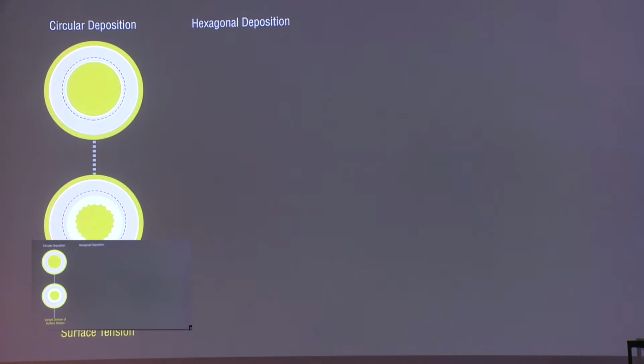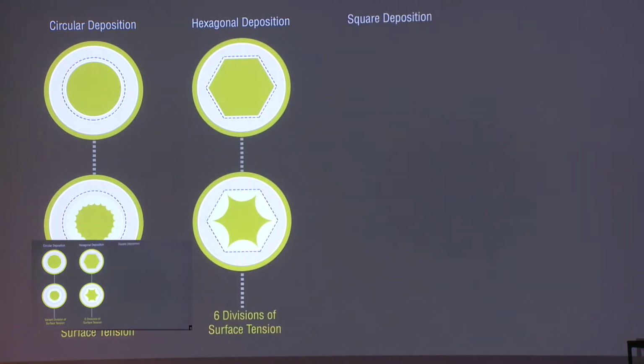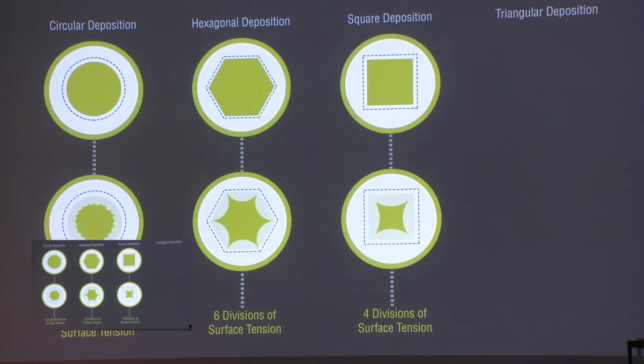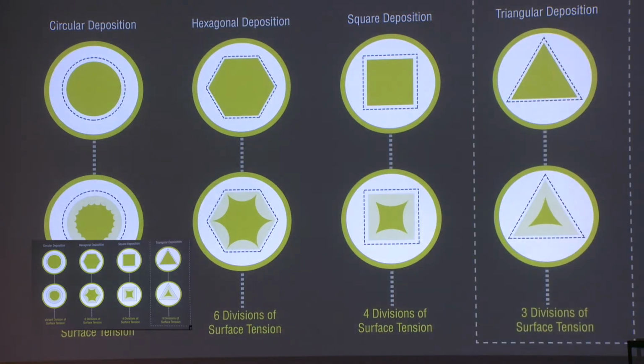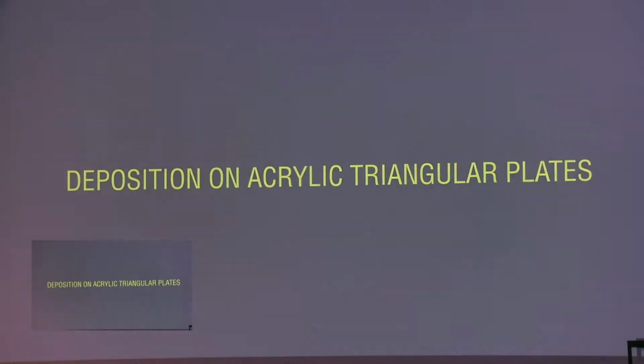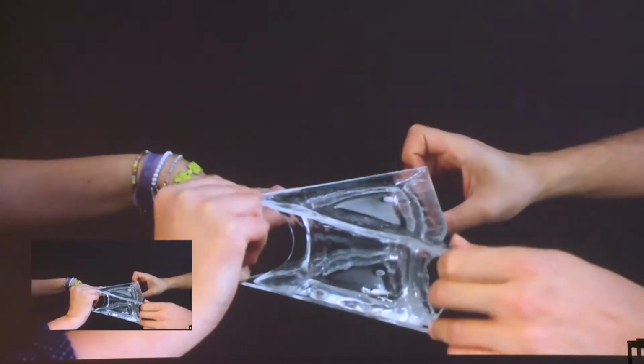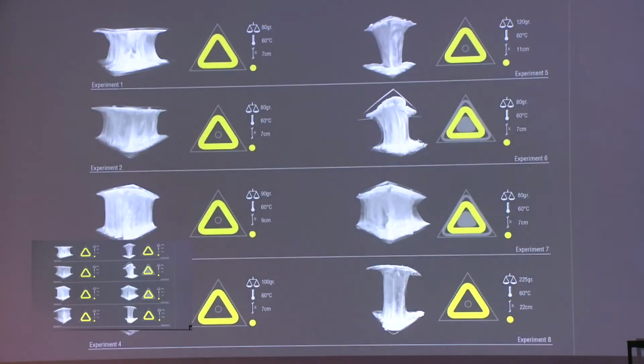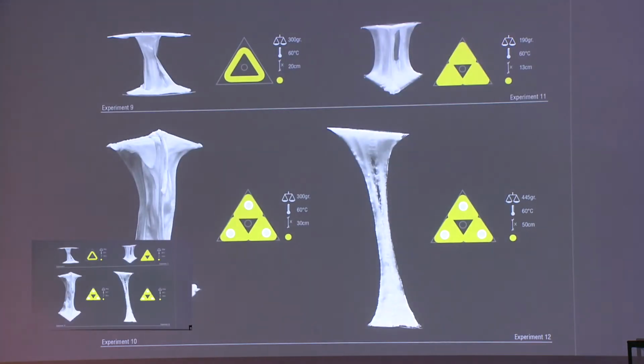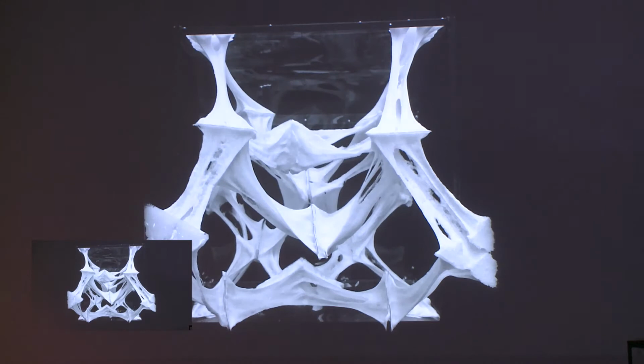After looking at all of those material simulation parameters, we evaluated which is the correct deposition and the correct shape of the plate that we need to use. So we came to the conclusion that the triangular deposition and triangular plate is optimal because the surface tension is divided equally in 3 parts to get a stronger section. So we started those experiments with triangular acrylic plates, still trying to deposit in lines and in solid mass, getting a better result with solid mass.